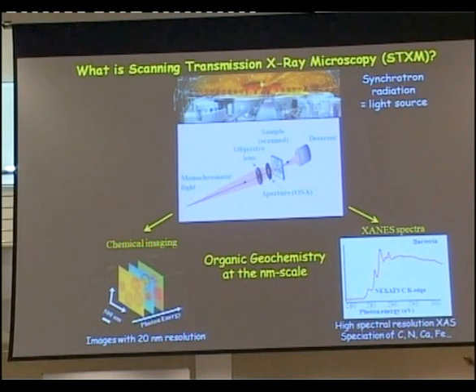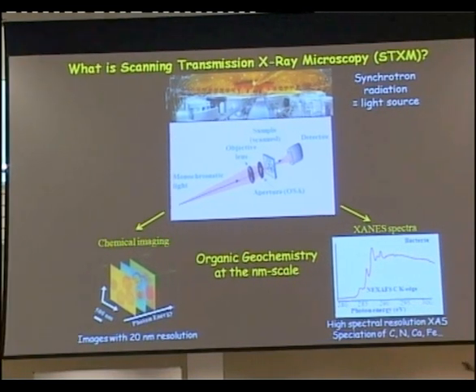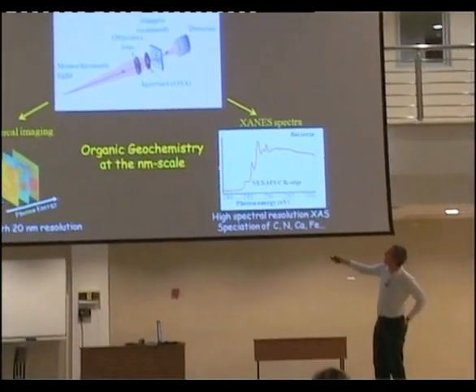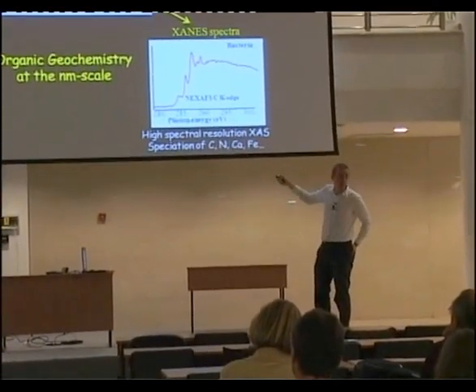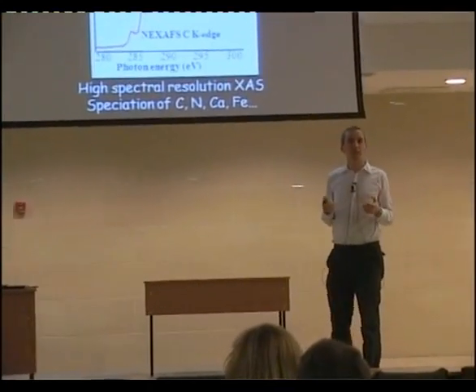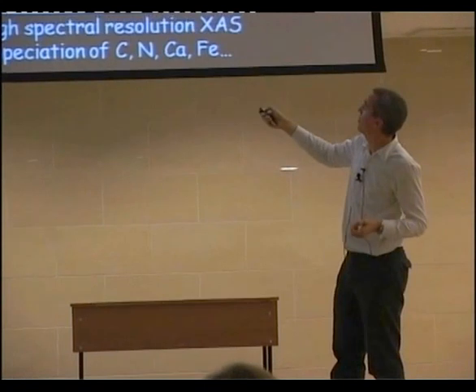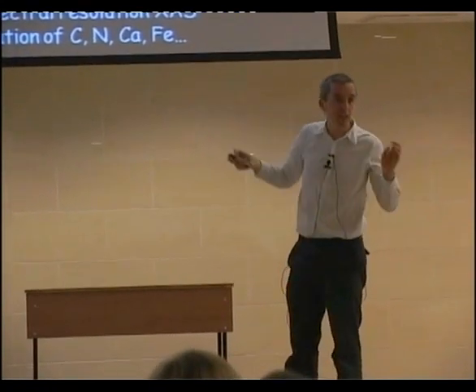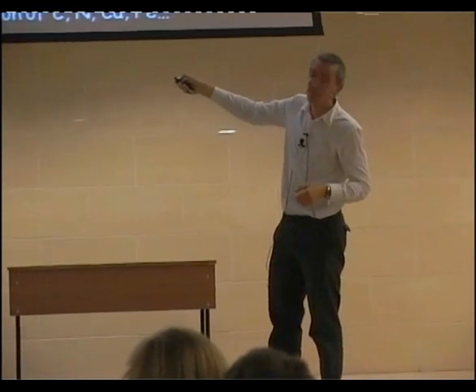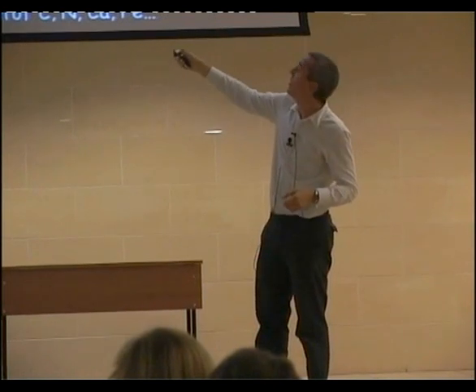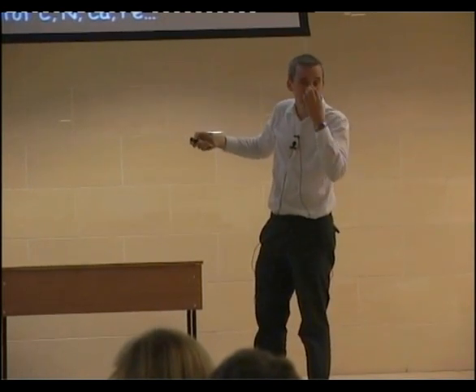But at the same time, you get also this spectra. And this spectra, you can get it for each pixel of this image. This measure the absorption of the X-rays. In Y, it's the absorption of the X-rays by the sample versus the energy. You can change the energy of the X-rays and measure the absorption for each energy. You get spectra. These spectra, they tell you something about the chemistry of carbon, for example. This is here for carbon. You see several peaks. Each peak relates to some type of carbon, like we can differentiate between aromatic carbon, carboxylic carbon, carbonate, and so on and so on. So yeah, you can do really chemistry.